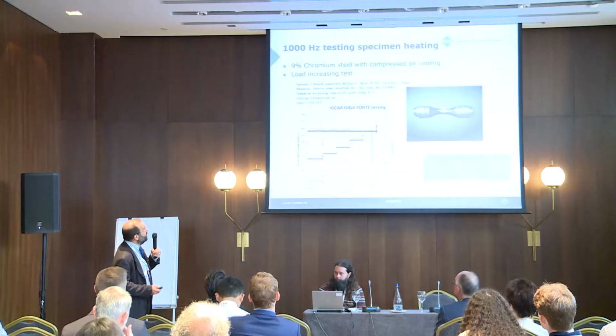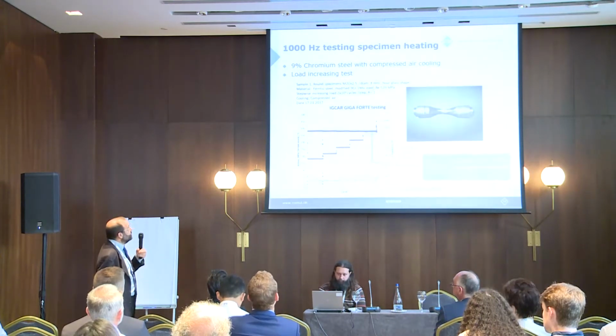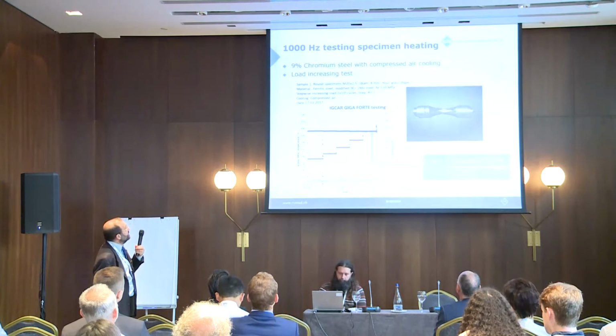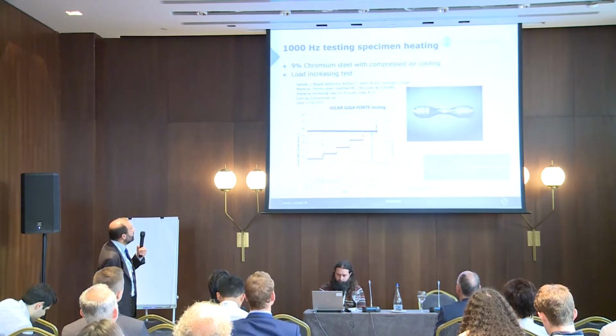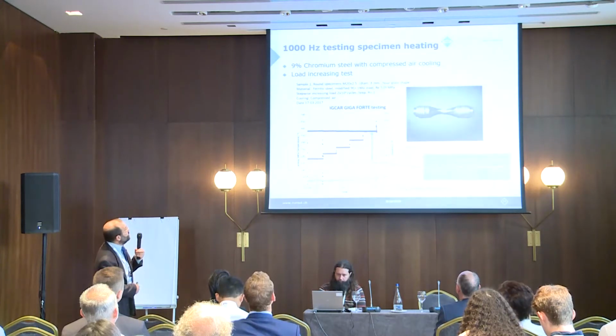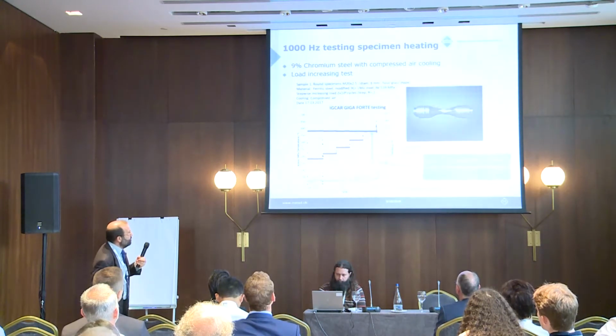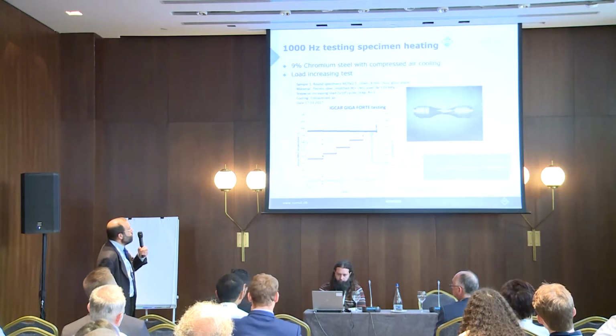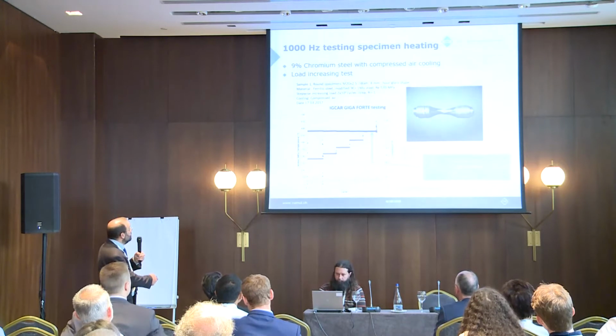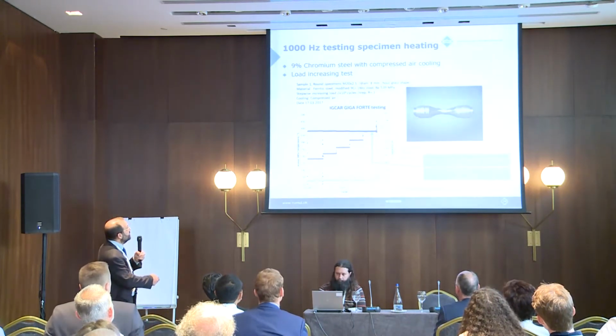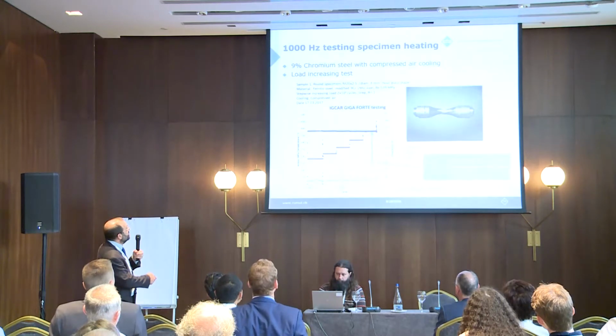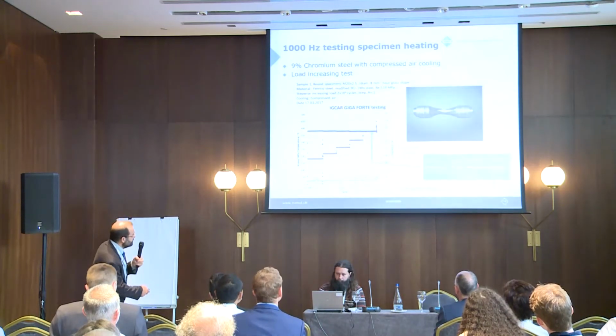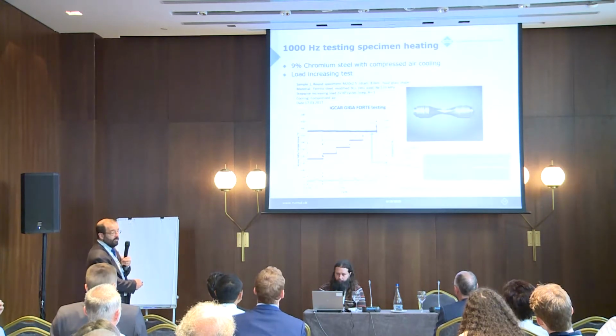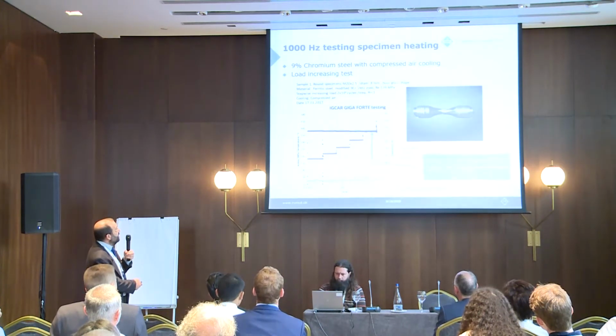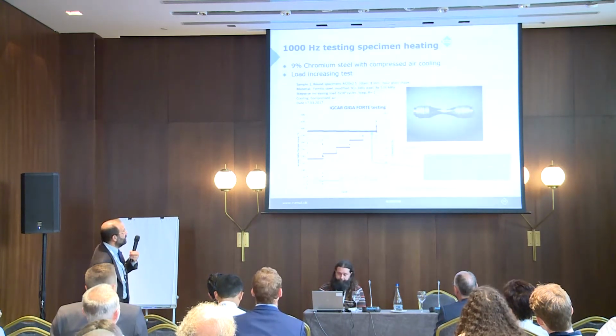Now I can show you some examples that we could test at RUMUL with specimens that have been provided by interested laboratories. The first is a 9% chromium steel, a material with some damping, which is known for that. And we conducted load increasing tests. The red dots is the load, the blue is the frequency, and the green is the temperature. By switching off the compressed air, we could illustrate how efficient the cooling is with the compressed air.